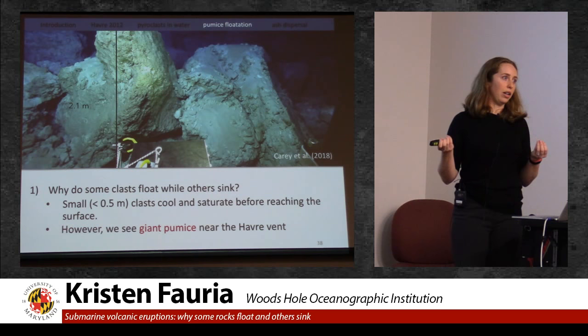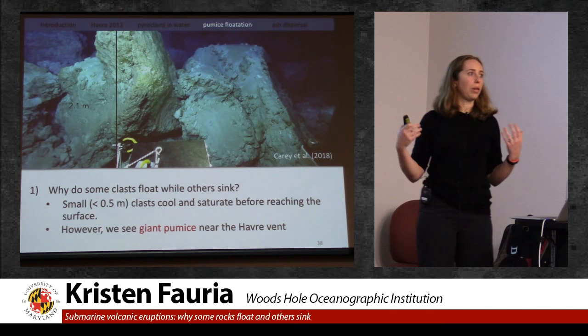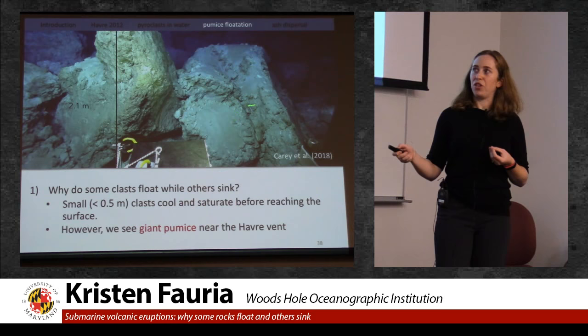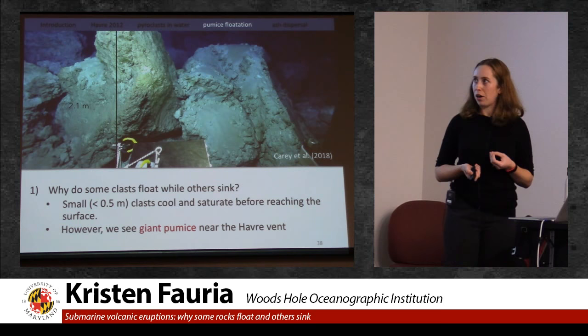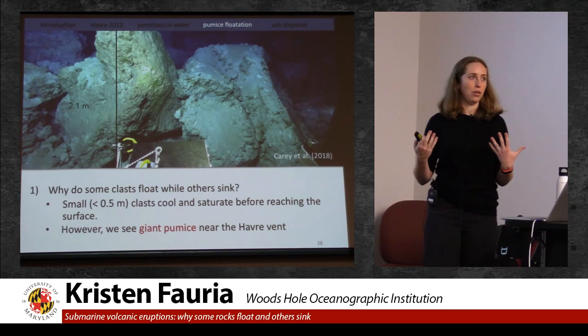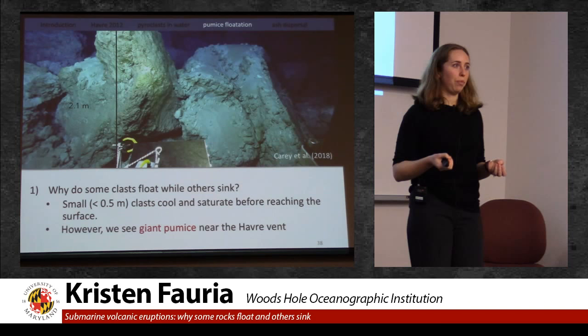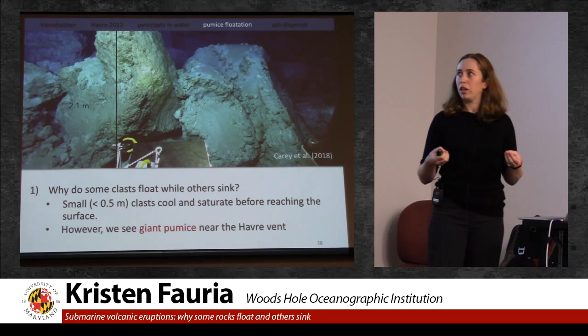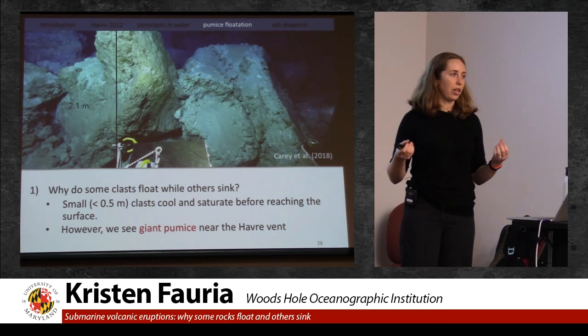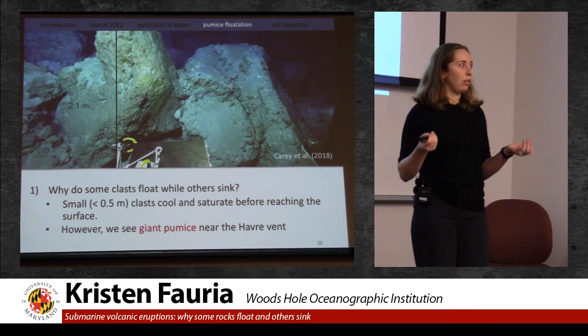We also found that small clasts can cool and saturate really fast, so they don't make it to the surface. And yet, as was pointed out earlier, we see these giant pieces of pumice on the seafloor really close to the vent. So how does that occur? So in order to at least start to address this question, we took samples from the raft and from fragments of giant pumice on the seafloor, and we heated them up and put them in liquid water. And we did the same X-ray microtomography experiments on these pumice as I did earlier and looked at the proportions of trapped gas versus liquid water inside.